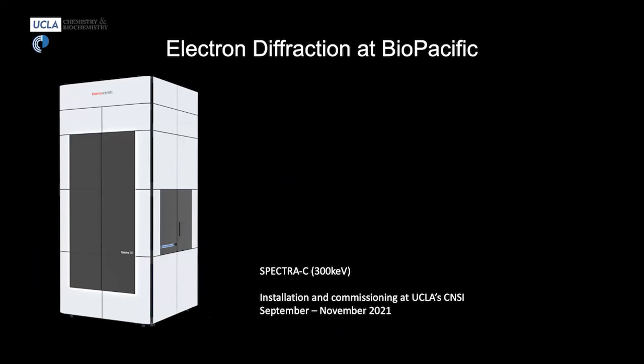Electrons, of course, have mass and charge. And so that charge is sensitive to electromagnetic potential or electrostatic potential in your molecule's crystalline array. And so in principle, you could see differences due to charge. You could also see interaction with light atoms because you're scattering from a screened Coulomb potential, which is derived from the nucleus itself and not from the electron cloud. And so that's what allows us, for example, to see hydrogen atoms more clearly than we would be able to see with X-rays.